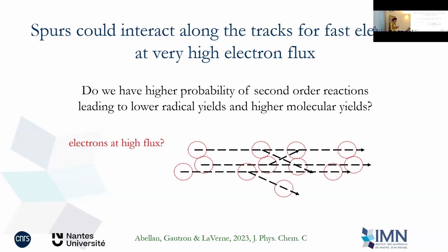Are these conditions adequate just in the homogeneous phase or also in the heterogeneous phase? We are talking about the spurs. This is heterogeneous. Yeah, we are still in the fast regimes. And this is very important because in that diagram, all the models in place in liquid electron microscopy start from the microsecond time scale, which means you are taking the G values that are tabulated and so on.